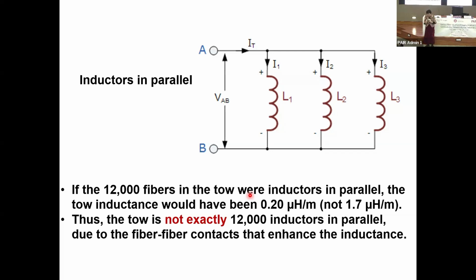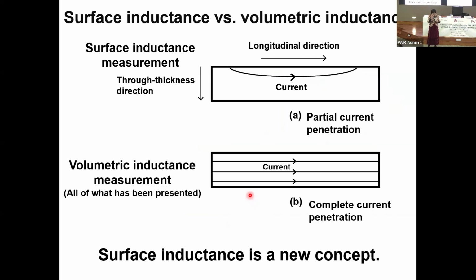So the tow is not exactly 12,000 inductors in parallel, and that's due to the fiber-fiber contacts that enhance the inductance. Now, I introduce another new scientific quantity. That is the surface inductance, as opposed to the volumetric inductance. What I talked about all along was volumetric inductance. Surface inductance involves using a surface current injected from the same surface. Okay, so the partial current penetration, as opposed to the volumetric inductance, which involves current completely penetrating the whole cross section.